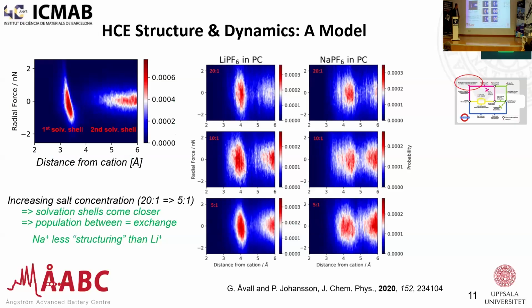And then, if you bear with me a little bit, complicated slide perhaps, but what you get from this, if you're actually studying the radial force from his methodology, you can basically see how you have first and second solvation shells around the cation. So you see either the solvent, or if you're very highly ion paired, you also see the anions. And you see how they are actually moving back and forth. And this, of course, is a heat map. So you see the more intensity, the more ions or solvents you have around.